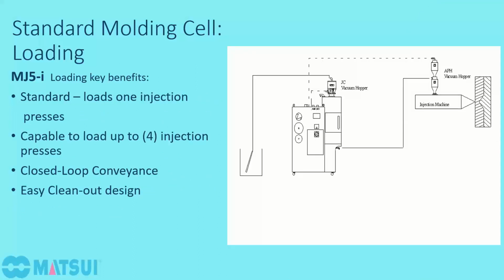In our standard configuration, the MJ5 will load from a Gaylord to the drying hopper, and then from the drying hopper, where again our discharge damper will be at the bottom, it will convey to the injection machine, and it also has the capability of feeding up to 4 injection machines. So you could feed up to 4 machines with one unit. Also, it has a very easy to clean out design. It has a large clean out door. The drying hopper is made of stainless steel, and the discharge damper comes apart easily. So if you're going to be doing a lot of material or color changes, it's easy to clean out.